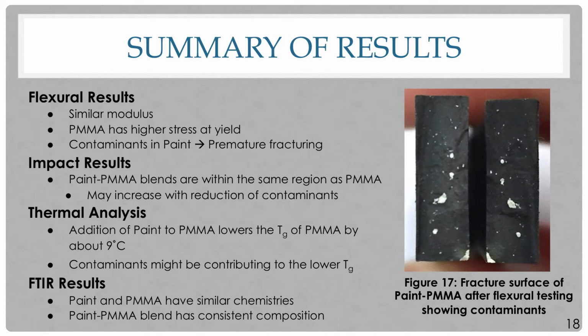So here's just a summary of the significant results that we got from each test. From flexural, we found that both the paint PMMA and PMMA shared roughly the same amount of stiffness, but the PMMA did have a higher stress at yield. This is perfectly fine though, because our blend is created from a waste material, and so it doesn't need to necessarily match the properties of pure PMMA.